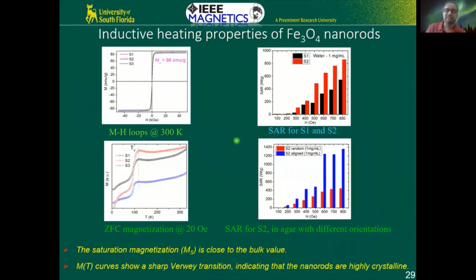Okay, so this one right here. Some of the highest SAR values in our lab, and some of these SAR values are much higher than what you will find in commercial use. So clearly, in the research lab, we can do much better in improving the SAR compared to the commercial instruments out there. We're trying to communicate with these companies to demonstrate that our particles are much better. You can see these are really, really high in nanorods.